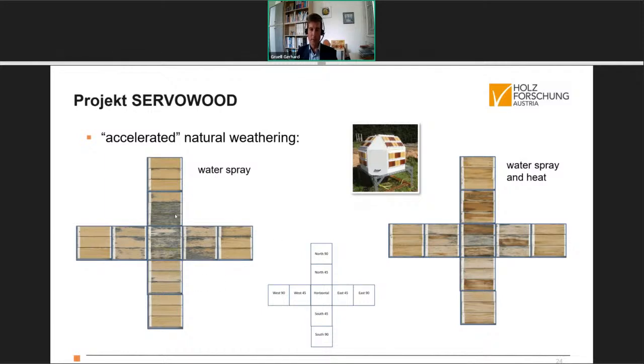This is just a glimpse of results of one of these setups, where you see the south and west and east facing surfaces, and here the north ones, and this is the horizontal surface on top, with different degradation. In general, you see here with additional water spray, in particular, high growth of fungi on the upper surfaces here, much less pronounced on the vertical surfaces, and much less pronounced on the south exposed surfaces. This is the rig with water spray and additional heat. Fungal growth was lower, but degradation of the coatings has proceeded much further, because heat seems to really accelerate degradation, and the samples are in even worse conditions here.